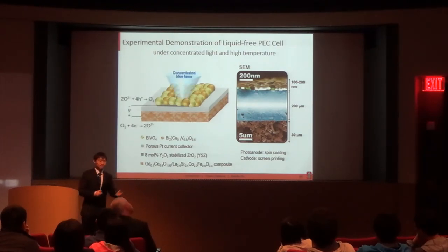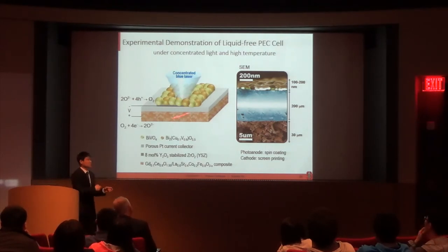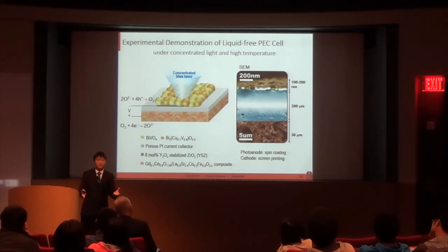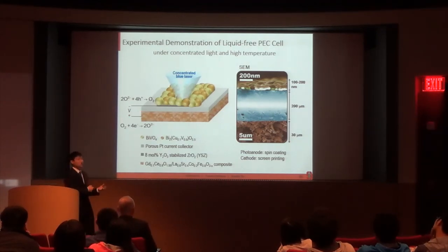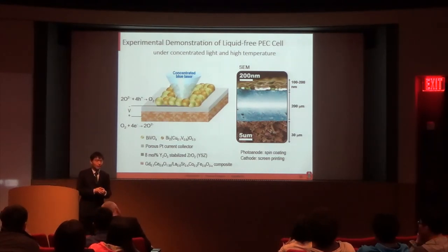For demonstration, we use a concentrated blue laser as a light source. And the device is placed in a single chamber environment with oxygen. So the counter electrode is now doing oxygen reduction reaction instead of water splitting reaction. So there's no water splitting. But it doesn't change the chemistry on the photoanode, which is oxygen evolution reaction. And we carried out the electrical measurement across this counter electrode and the buried current collector.